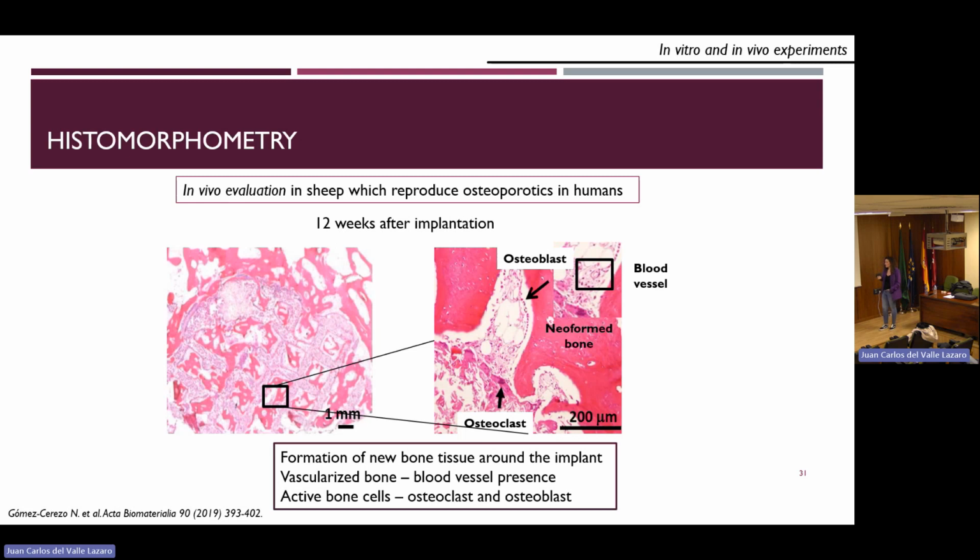We analyzed these areas more closely and observed active osteoblasts, some osteoclasts maintaining the balance of the growing tissue, and even blood vessels through the structure, which means that our materials were very promising. We obtained about 25% of bone regeneration after 12 weeks.